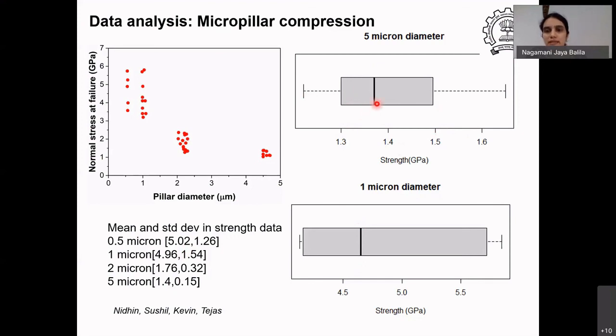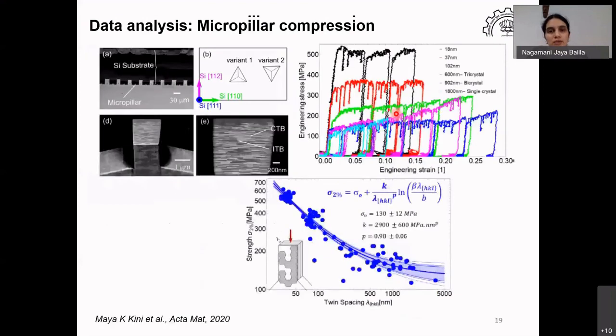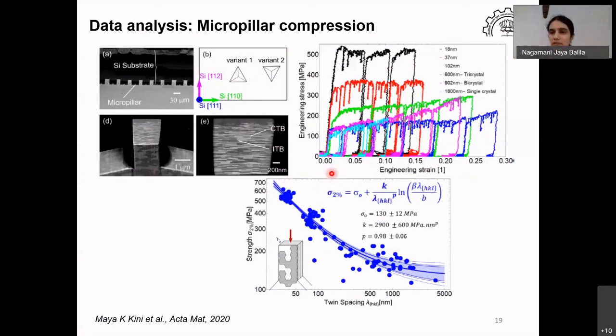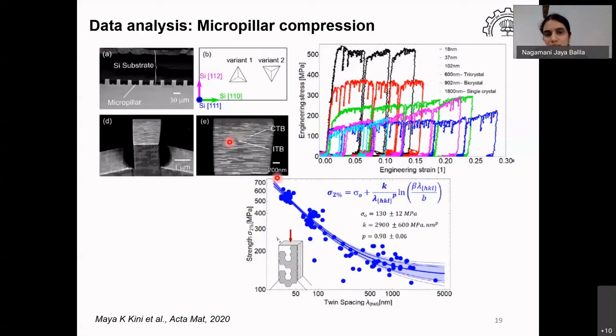There is a 95-percent confidence interval that's plotted — in R I'm sure this allows all of these to be viewed together. If I look at the individual spread in the data for each pillar diameter — say 10 to 12 data points at 1 micron and 8 to 10 at 5 micron — one way is to calculate the mean and standard deviation. But if you do it as a box plot, you can see that the median is not the same as the mean and that the median is skewed to the left in both cases, telling you the distribution is not normal. The one-micron case has a very large spread whereas the other has a smaller spread.